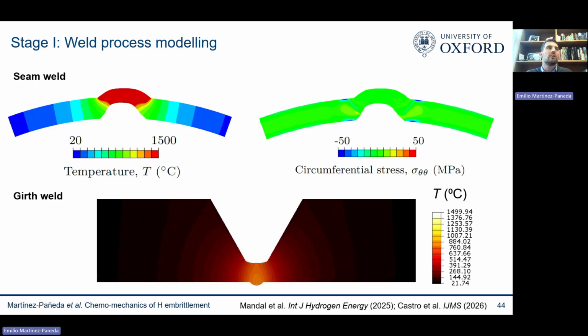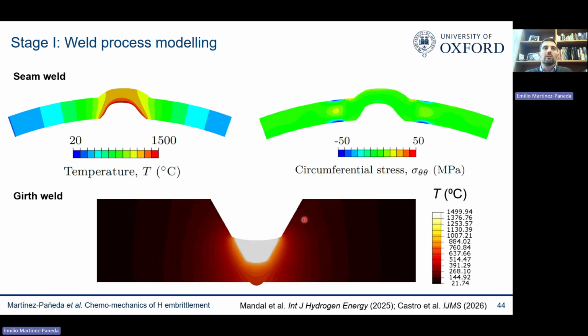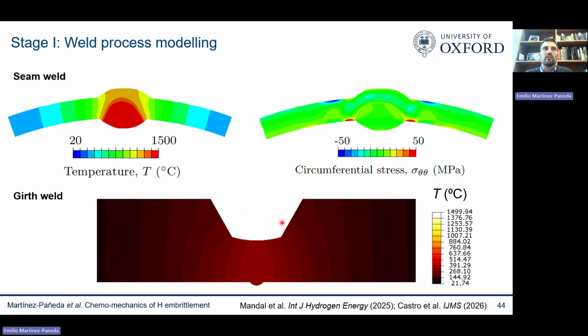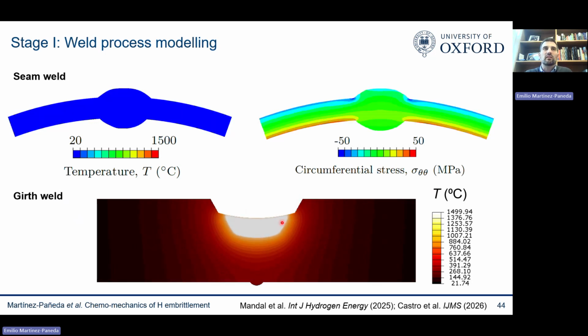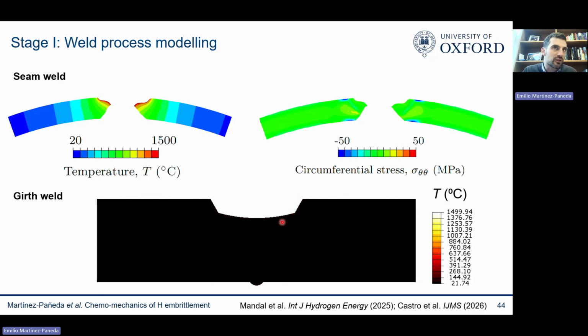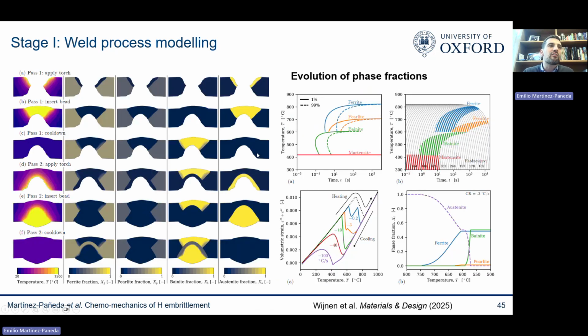This is a welding process. On the top is a seam weld, on the bottom is a girth weld. You see how we simulate the different passes, and then you predict not only the temperature distribution and residual stresses, but also, depending on your cooling rates, what is your phase fraction - ferrite, pearlite, bainite, austenite - and how this changes.